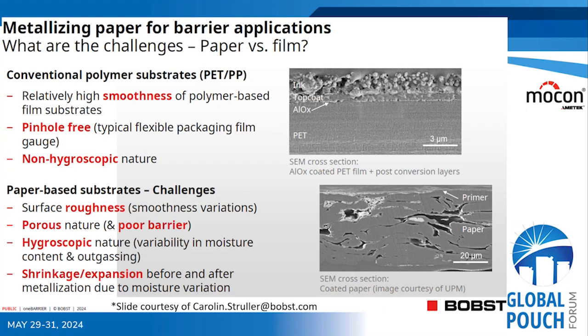A challenge is that paper itself is very hygroscopic. It can swell in the presence of high humidity. You take it to an extreme, and it can totally just break down and fall apart in a very jungle-like, high temp, high humidity environment. As it can swell, it can also shrink. And so dealing well with the shrinkage and the expansion is a lot trickier if you're trying to apply a coating to it and then also have it survive its life cycle as a package. So there's a lot of nuances in art and challenges with coated papers, and creating them, and making sure that they're good.